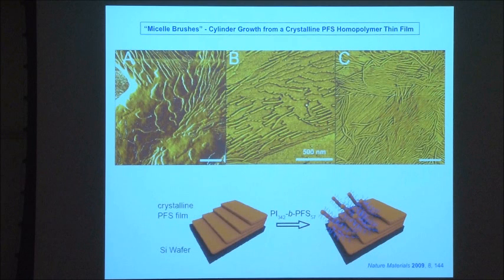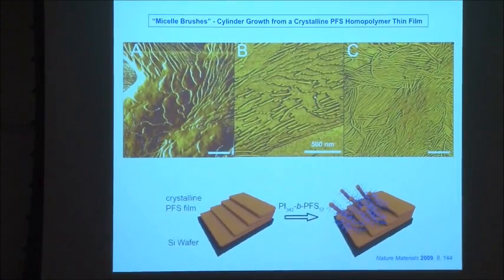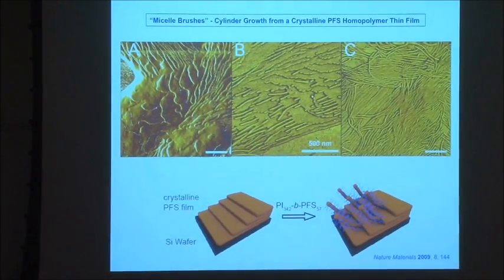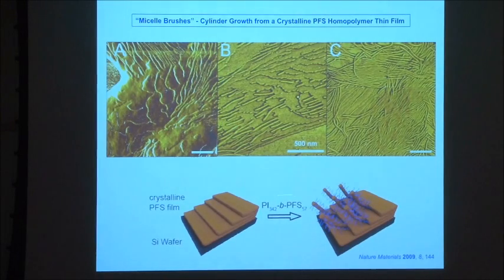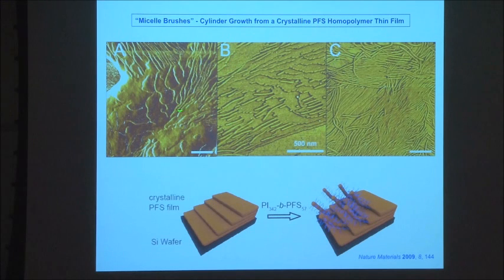So you can take a homopolymer film. So this is dimethyl PFS homopolymer. You cast it as a film. You can anneal it to make it crystallize. You can then dip this in hexanes, add the block copolymer in the form of unimers, and this will initiate off of the crystallites in the surface of the crystallized film. And you can see here in B, this is early stages after adding the block copolymer. You can see cylinders starting to grow off of the surface, off of the steps in the surface. And in the end, the surface is completely covered with spaghetti. And you have this sort of micelle brush layer on the surface.